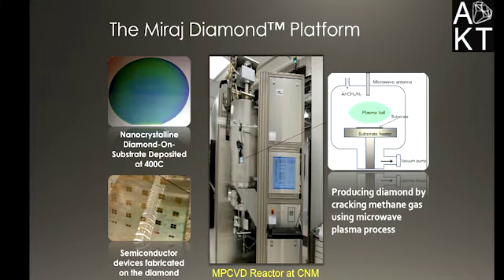So we debuted the Miraj Diamond platform, which combined these two novel features, where we can put diamond down at very low temperatures, not only on silicon, but also on these other wide bandgap materials like gallium nitride, like silicon carbide and the like. And we're actually able to make semiconductor devices from the diamond layer on top. And now, instead of having these systems, which are very, very large and would never fly in a commercial sense, we actually have very compact systems, like the MPCVD reactor they have at CNM, which is fully automated. So we now have a commercially feasible way of producing these materials.